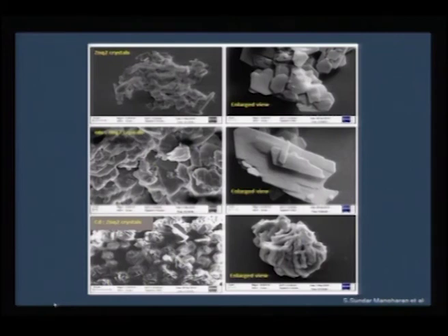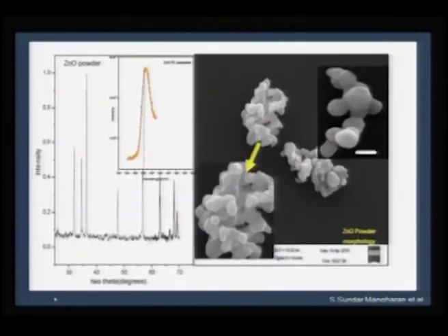And you can also see with just doping a little amount of manganese or cadmium, the morphology of the zinc peroxide crystal changes abruptly with the doping system. As you can see, this cauliflower sort of bundles coming out of cadmium substitution, platelet type coming out of manganese. Nevertheless, they do affect the surface morphology of the corresponding oxide. For example, zinc peroxide, if I decompose, I get this sort of nearly spherical platelets of zinc oxide, and the beautiful emission characteristics of band to band emission is also seen here.